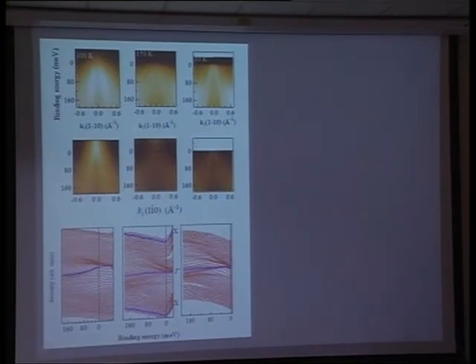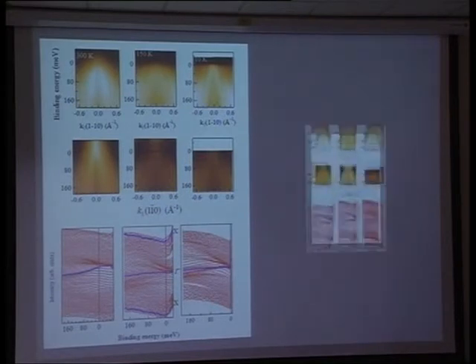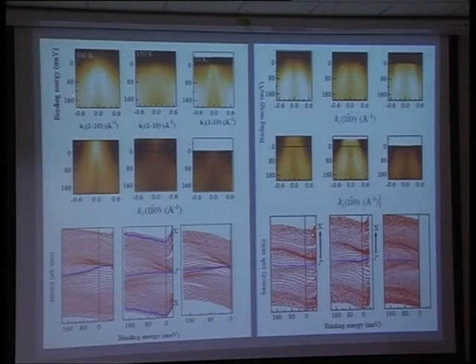Now you look at the temperature dependence. So here we have shown helium 1, maybe I'll show both of them, helium 1 and helium 2. So these are the raw data. And here we show the spectral density of states. So you have this ARPES data divided by the Fermi distribution function. So that gives you the spectral density of states. You can see that these two bands, which are quite dispersive, become more like this. And I don't know if you are able to see the lines here, you can see there are two distinct bands which are coming up. Here, of course, at 10 Kelvin, you can see these two bands very clearly. But in helium 1, these two bands appear a little away from the gamma point, as we have seen in the earlier data.